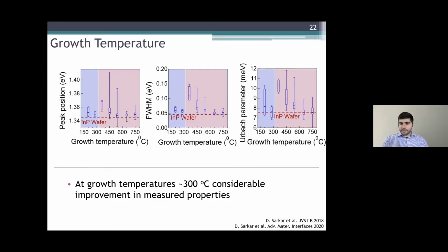And this was a puzzle for us. How we understand what's happening now is that the extrinsic defect density being incorporated at these lower temperatures is lower, and that has to do with our capping layer, we think, because we use a substoichiometric silicon oxide capping layer, which disproportionates to silicon plus SiO2. So the result is that we can get low temperature materials which look pretty good.